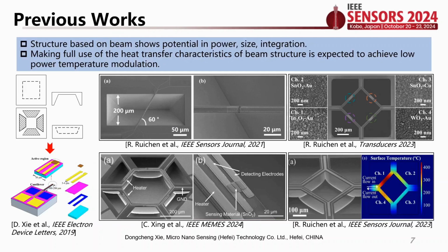The traditional structure of a metal oxide gas sensor is to make the main parts of the sensor, including the micro heater, the detection electrodes, and the sensitive material, on a closed or suspended membrane. In our previous works, we tried to make the sensor on beam structures, and we found that structures based on beams show potential in power, size, and integration. Meanwhile, by making full use of the heat transfer characteristics and the temperature distribution of the beam structures, it is expected to realize low power temperature modulation.